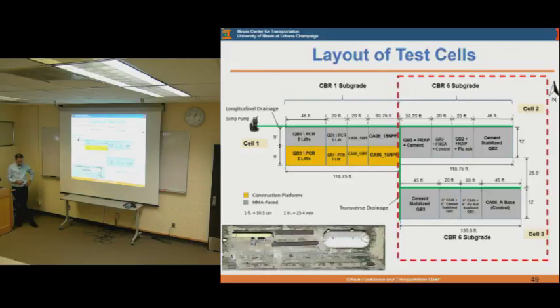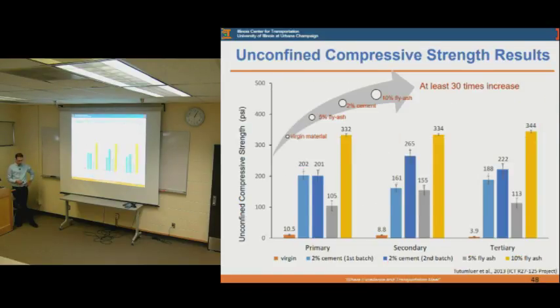So the reason behind stabilizing the quarry byproduct is that, as you see here in those orange columns, the strength of the quarry byproduct by itself is very low. But when it's stabilized with fly ash or cement, as low as 2% cement or 10% fly ash, we can get unconfined compressive strength increase up to 30 times in some cases.